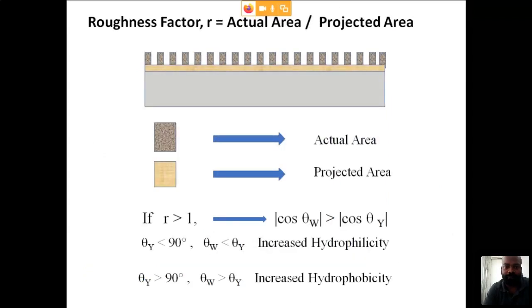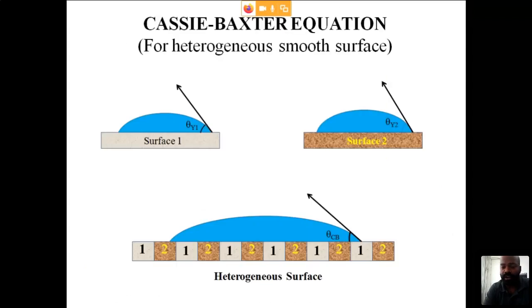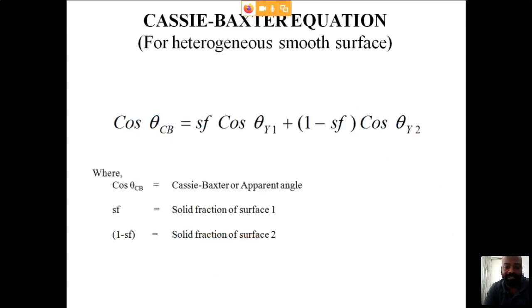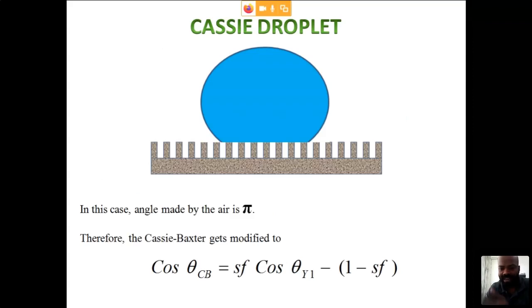Now again, the representation of the roughness factor. And Cassie-Baxter: if you remove the concept of roughness and only bring in the heterogeneity of chemical composition, with two surfaces involved, the resultant equation will be something like this, a combination of the roles played by all the solid fractions. This is the Cassie droplet state. It is the representation of the droplet on a lotus leaf. The droplet hangs on a rough surface filled with air. In all these roughened surfaces, there will be air in the gaps. This air works as a second surface, so the equation becomes this way. This is called the Cassie droplet.